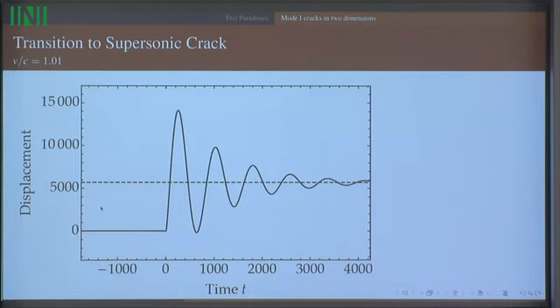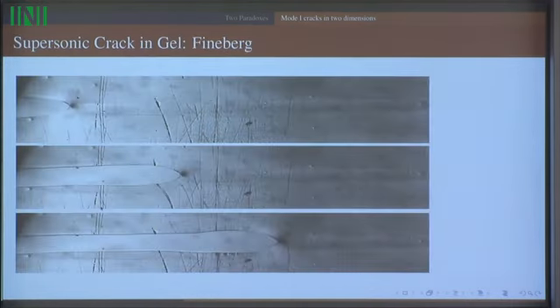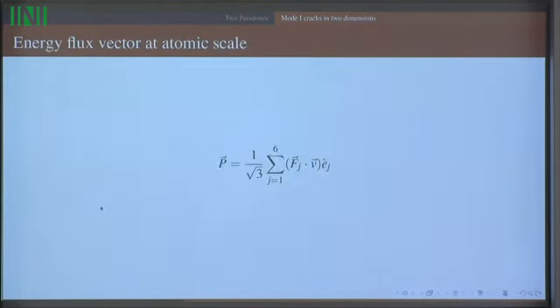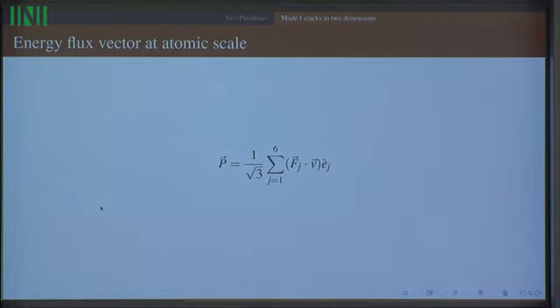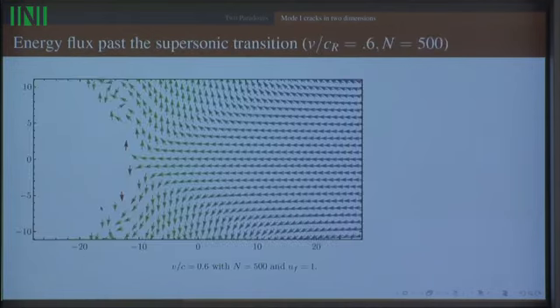It's just different. I have here a photograph of a crack going supersonic in a gel by J. Fineberg, and this characteristic overshoot and then undershoot is evident there. So it's at least consistent with this picture of a large-scale ringing after the crack. And I'll close with just some pictures of the energy flux here.